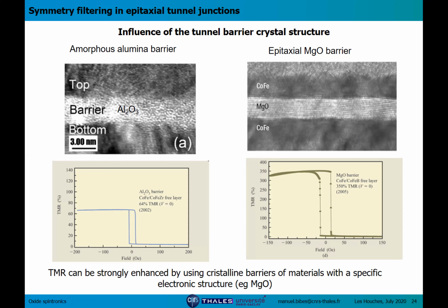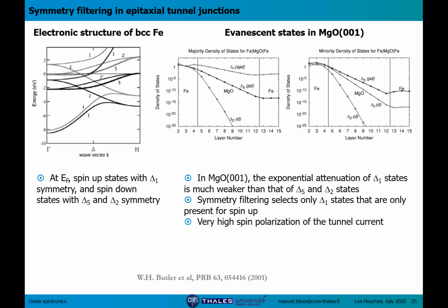So why is the TMR so high when one uses epitaxial MgO barriers? This has to do with the electronic structure of the MgO barrier and also the electronic structure of the ferromagnets, BCC iron or BCC cobalt. So let's have a look first at the band structure of BCC iron. This is maybe not very easy to see, but let me take you through that. Here at 0, you have the Fermi level. In black, you have the bands for spin up, and in gray, you have the bands for spin down. You see that at the Fermi level, for spin up, you only have this state labeled delta 1, the state with the delta 1 symmetry. On the other hand, for spin down, you have states present with delta 5, delta 2 prime, and delta 2 symmetries.